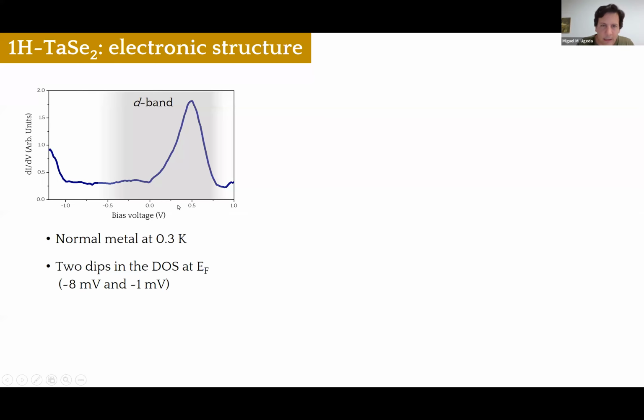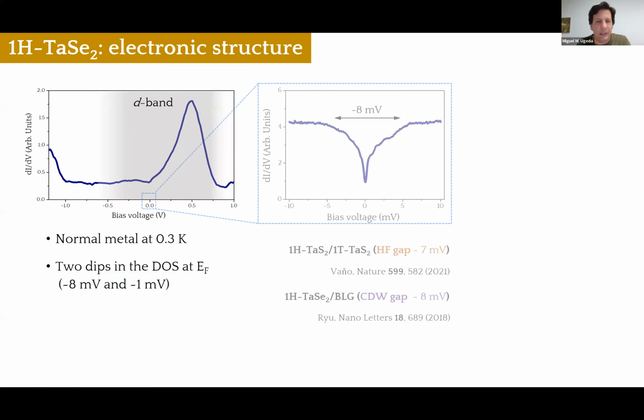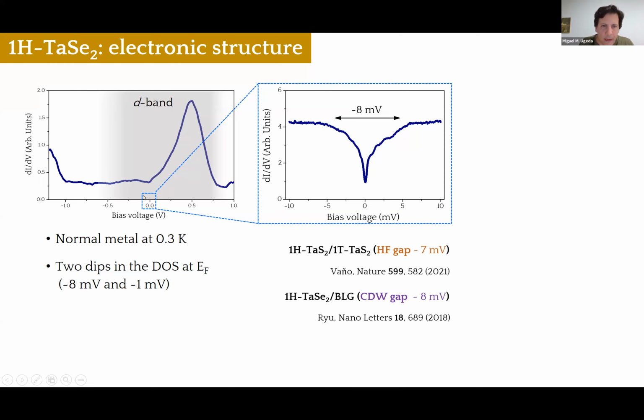But interestingly, if we zoom in on this region close to the Fermi level, we see the emergence of one dip in the density of states around the Fermi level with a width of about 8 milli-electron volts. So the origin of this dip is not entirely clear. Several groups have attempted to attribute it to different things in the past.